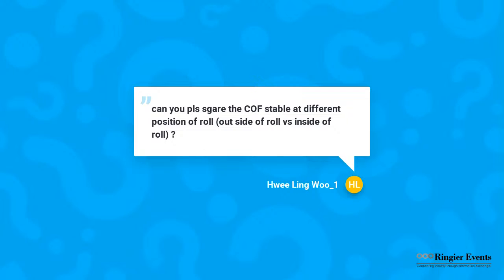Can you please share the COF stability at different positions of the roll, outside of the roll versus inside of the roll? In our slide, we showed the COF, I believe this is referring to the COF on the PE side in the roll. In one of the slides we showed the PET surface COF that varies from inside to outside the roll, but for the PE side it will not vary.